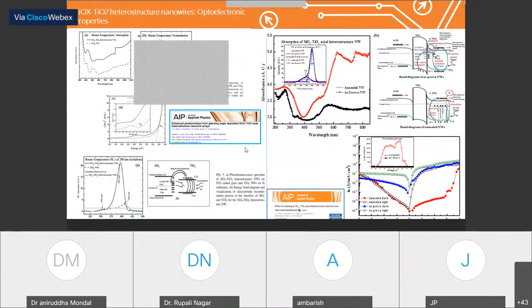And then we have annealed the samples. Due to the annealing of the samples, the defect states between the silicon monoxide and the titanium dioxide have decreased, and due to the decrease of that, the PL intensity has decreased, which is shown from here.